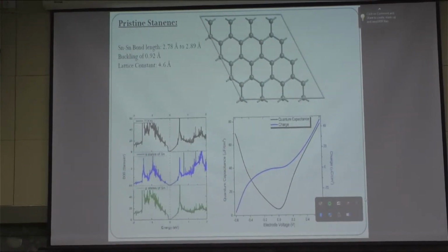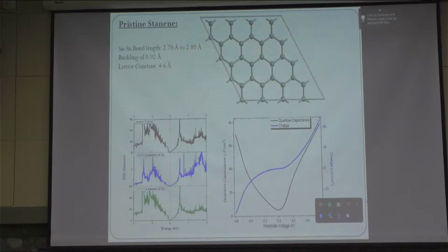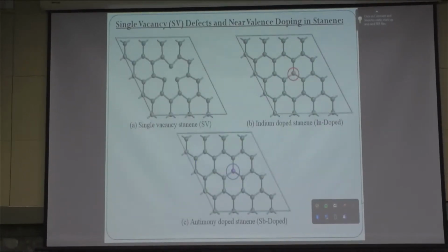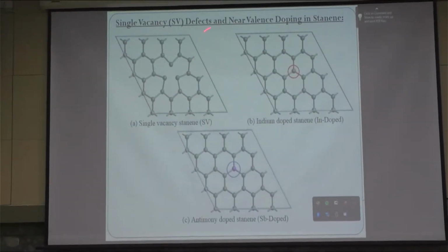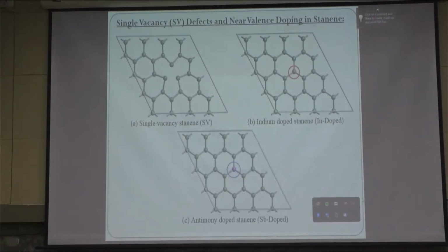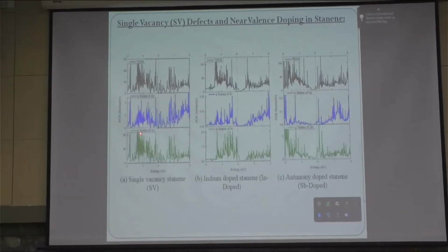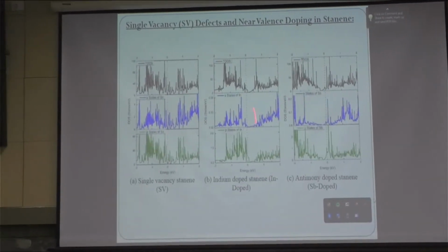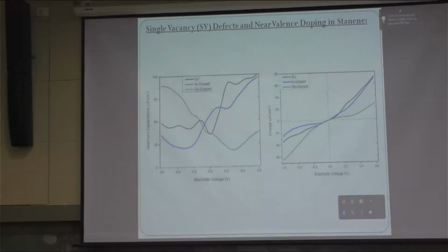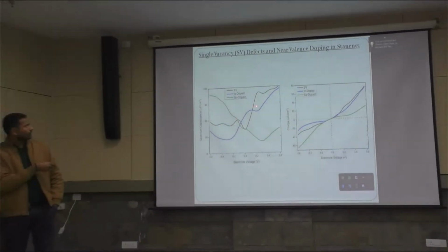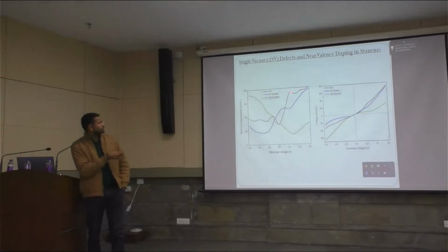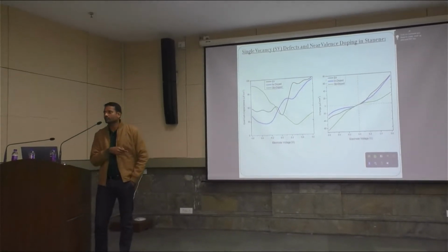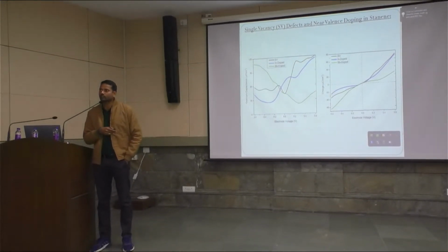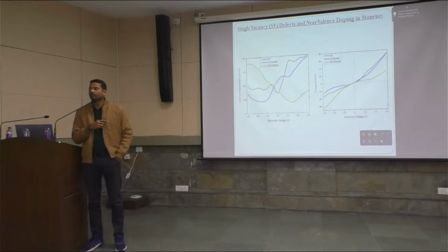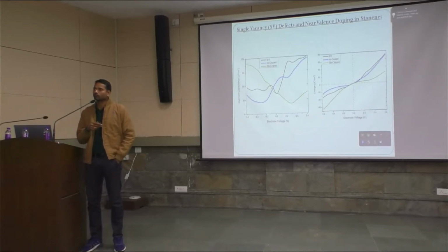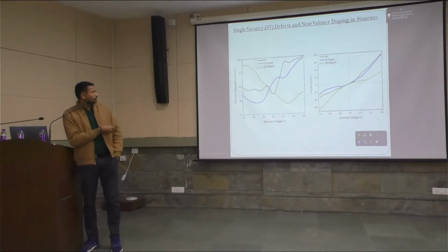To explore different ways of enhancing the quantum capacitance of stanene further, we have introduced a vacancy defect in stanene. After introducing the vacancy defect, we found that the band gap is still 0, but the quantum capacitance increased very much. The new quantum capacitance is approximately 120 microfarad per centimeter square. Earlier it was 77. The vacancy defect increased the quantum capacitance to 120 microfarads. However,